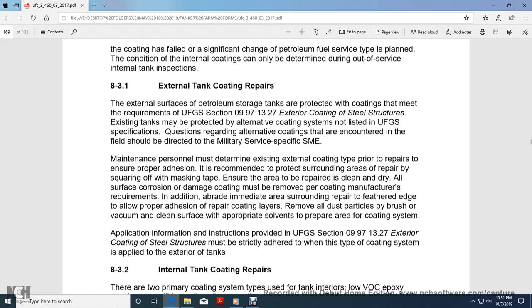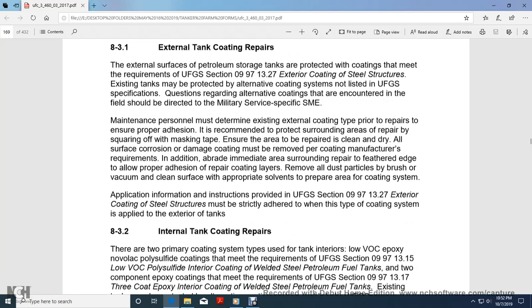To ensure proper adhesion, it is recommended to tape the surrounding area of the repair, squaring off with masking tape. Ensure the area to be repaired is clean and dry. All surface corrosion damaged coatings must be removed per the coating manufacturer requirements. In addition, abrade the intermediate area surrounding the repair and feather edge it to allow proper adhesion of the repair coating layers. Remove all dust particles by brush or vacuum, and clean the surface with appropriate solvent to prepare the area for the coating system.